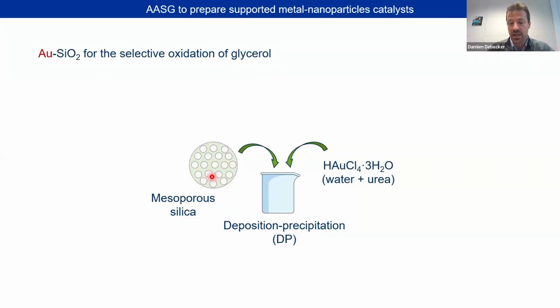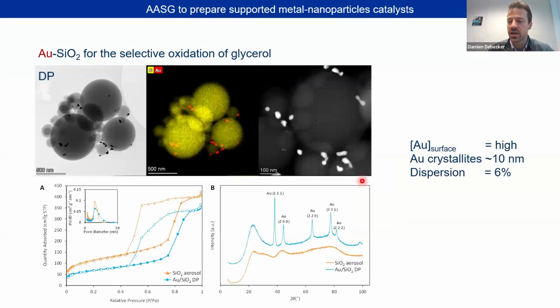For example, you could take a silica that is made by aerosol. Why not? Taking a pure silica and then do what everybody does for gold, a method that is called deposition precipitation with urea. And if you do that, this is the kind of materials that you get. So you see the spheres, you see the mesoporosity because it was done by aerosol, very nice. But then when you put the gold on top of that, you see those dark or red or bright spots in the electron microscopy images. These correspond to quite large gold particles that accumulate on the surface of those spheres.